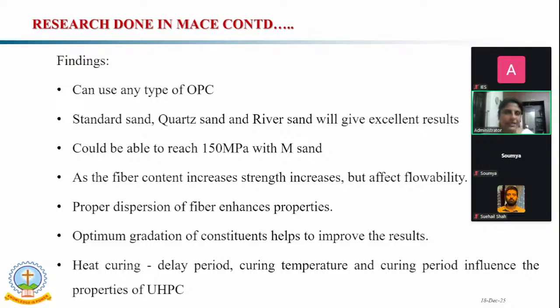Then in the case of fiber content, in the parametric study we varied the dosages of fibers and the aspect ratio of fibers. Finally, what we reached is that as we increase the dosage of the fibers, that increases the performance characteristics, but it negatively affects the flowability. I will show some figures on that. Proper dispersion of fiber enhances the properties of the UHPC. As we increase the aspect ratio also, that increases the performance of the UHPC, flexural as well as compressive strength. But that will be only up to an aspect ratio of 100.